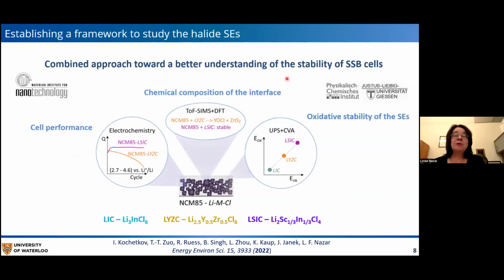So we worked together with Jürgen Janek's group, at the Justus Liebig University in Gießen, to try to understand the nature of these interfaces a little bit better. And sort of our general combined approach is shown here in this diagram. So what we decided to focus on was 3 of these metal halides: a lithium indium chloride, a lithium yttrium zirconium chloride, and our lithium scandium indium chloride.